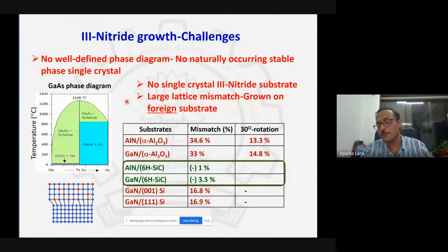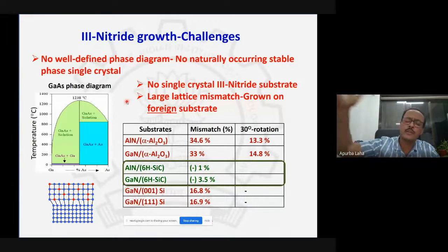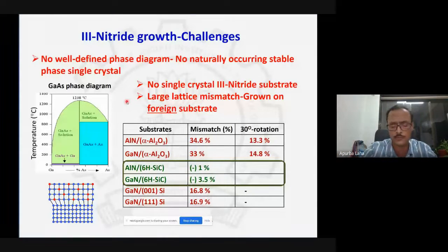If you want to grow gallium arsenide based devices, you have a nice gallium arsenide substrate available in the market. You buy this substrate, and then you grow the multiple layers of heterostructures required for your device, for example, LEDs, photodetectors, or whatever the purpose may be. But in particular, for gallium nitride materials, we do not have a single crystal substrate available. Although recently there are some single crystals available, they are not large area, and they are grown differently, not by the typical single crystal growth technique. So we have to look for another suitable substrate.